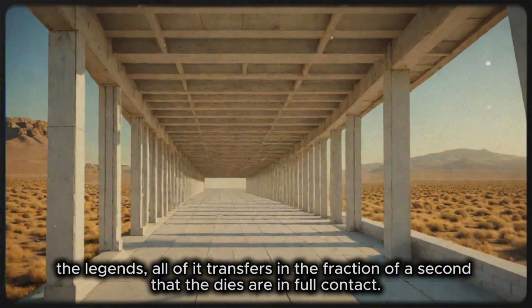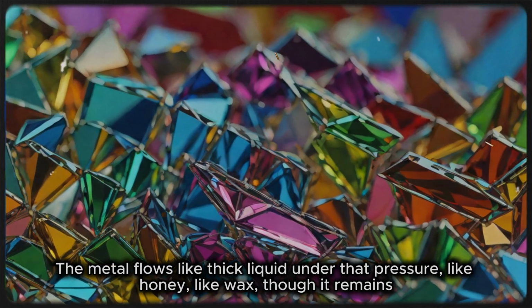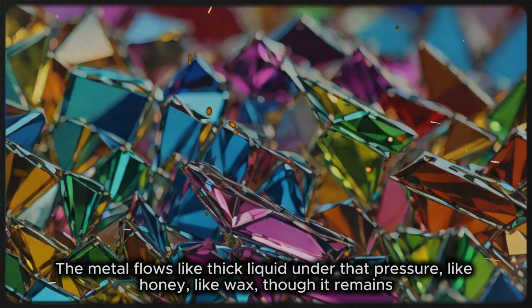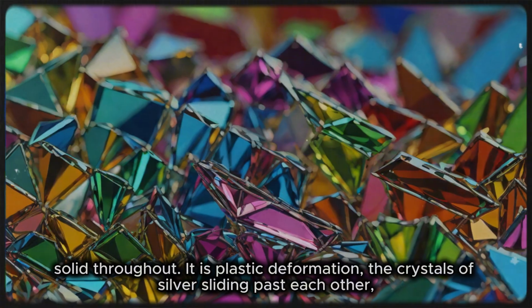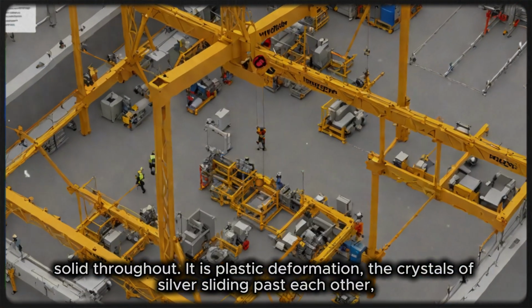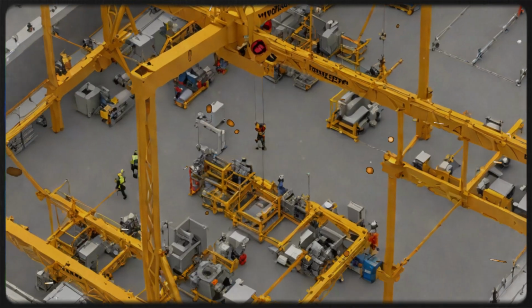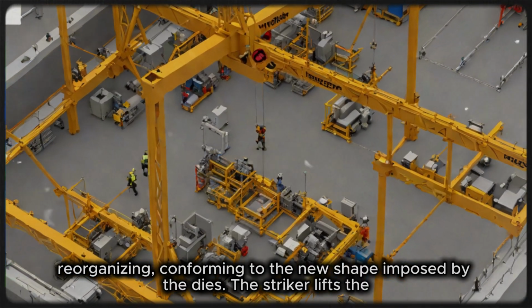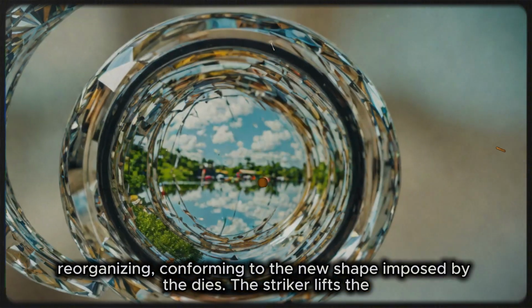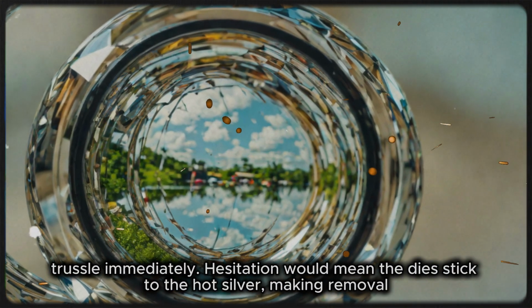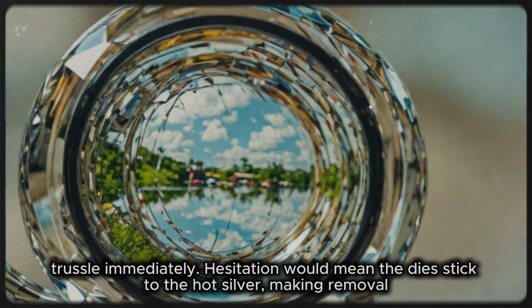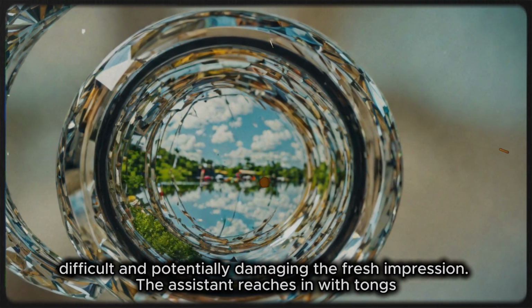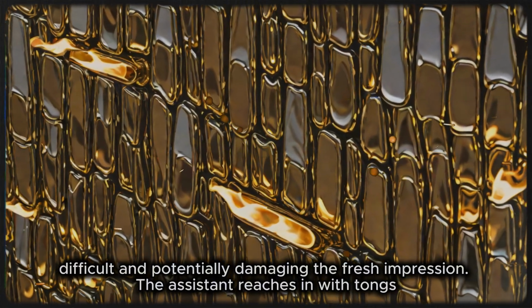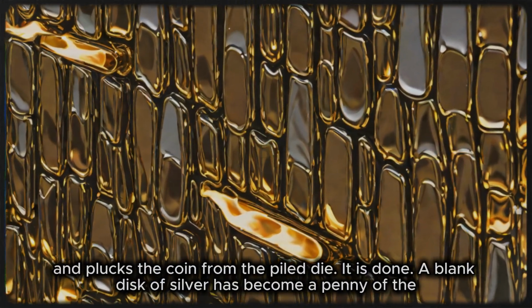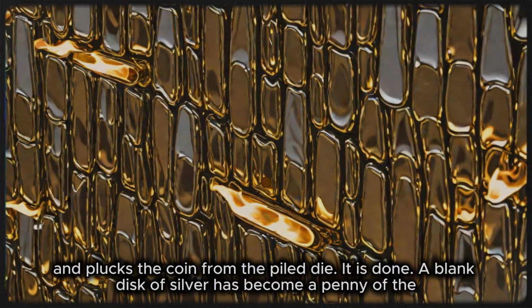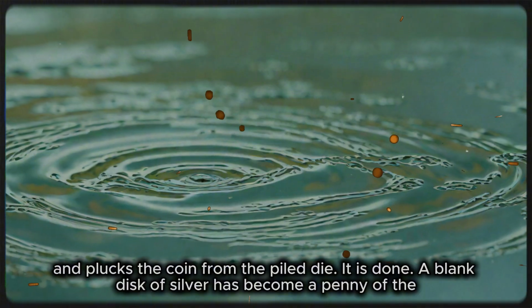The metal flows like thick liquid under that pressure, like honey, like wax, though it remains solid throughout. It is plastic deformation, the crystals of silver sliding past each other, reorganizing, conforming to the new shape imposed by the dies. The striker lifts the trestle immediately. Hesitation would mean the dies stick to the hot silver, making removal difficult and potentially damaging the fresh impression. The assistant reaches in with tongs and plucks the coin from the pile die. It is done. A blank disc of silver has become a penny of the realm.